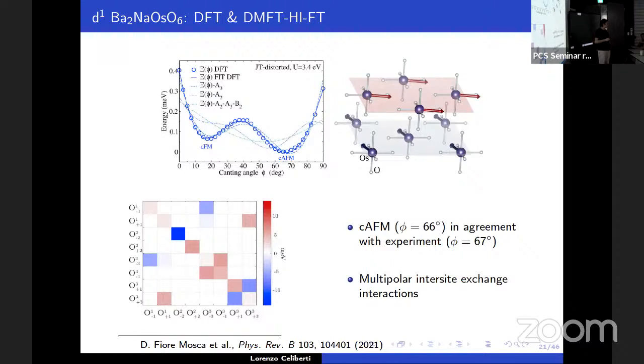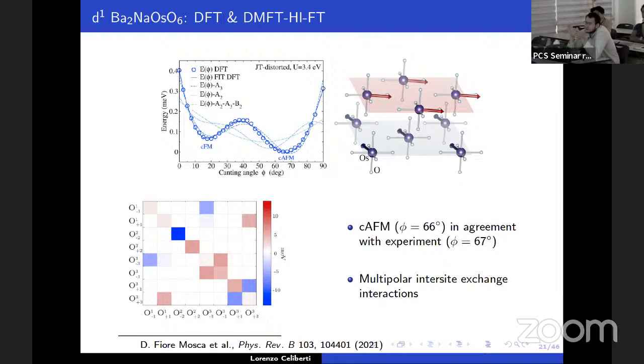To have some better understanding, you have both this antiferromagnetic-like ordering and also octupolar ordering simultaneously. Yeah, because what you see here is magnetic dipoles. You don't see octupoles. I mean, you see quadrupoles from the Jahn-Teller distortions, because they're connected also to the Jahn-Teller distortion. But how can you probe these hidden orders? Maybe you can comment more on that.